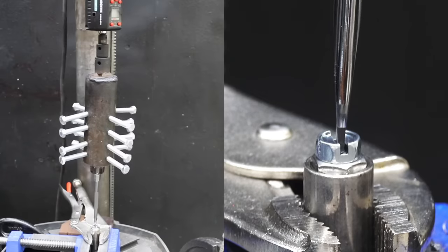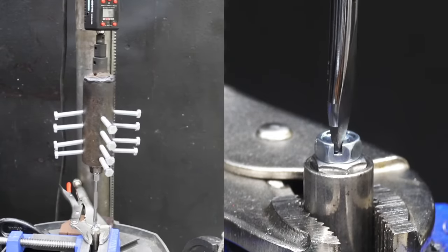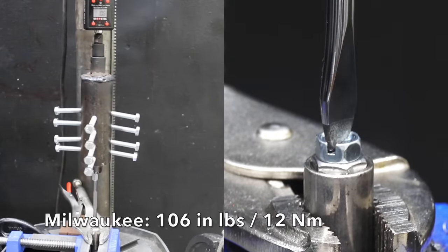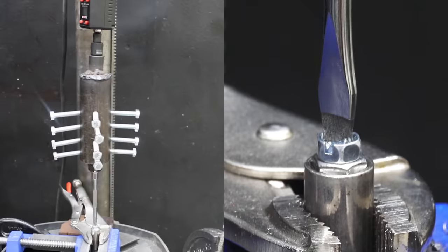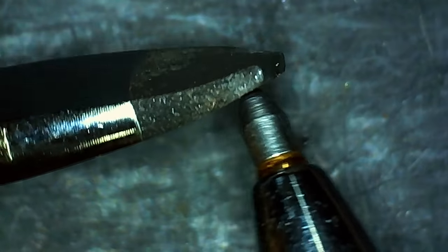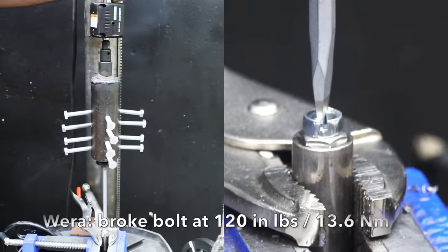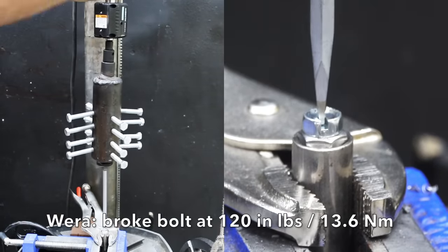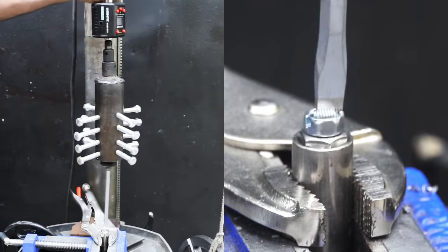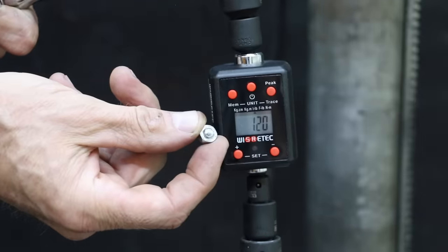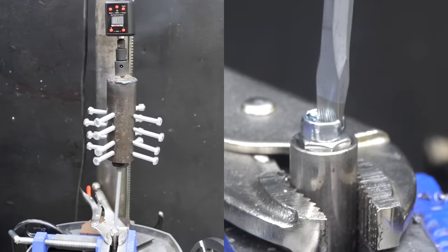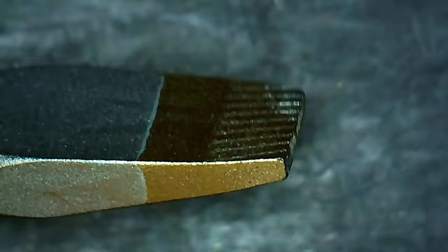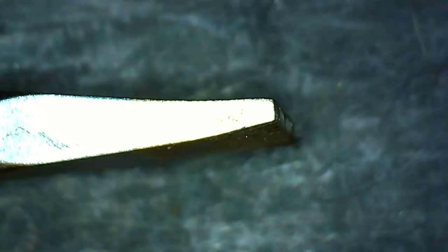The Milwaukee only has a blade thickness of 1.05 millimeters, and it did the best yet, finally letting go at 106 inch pounds to take the lead from Felo. However, the screwdriver did experience a pretty bad bend. And the Wera, with a blade thickness of 1.22 millimeters, broke the bolt at 120 inch pounds. Very impressive. Let's try this again. And the Wera did nearly as well the second time, this time letting go at 117 inch pounds. The blade does have a small bend.